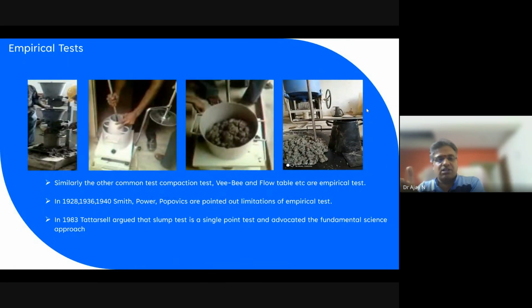We also have some other tests. Similarly, we have VB, compaction, and flow table tests. All these depend on the application point of view, because we generally do not do compaction in the field. All these tests are conducted in the laboratory. The compaction test is based on the height of the concrete, so we check the segregation or the cohesiveness of the mix. In VB, we check how much time it takes to change shape from conical to circular, so we measure workability with respect to time. And in the flow table, again we measure distance.